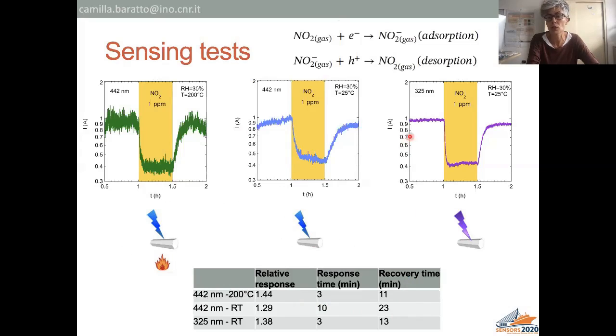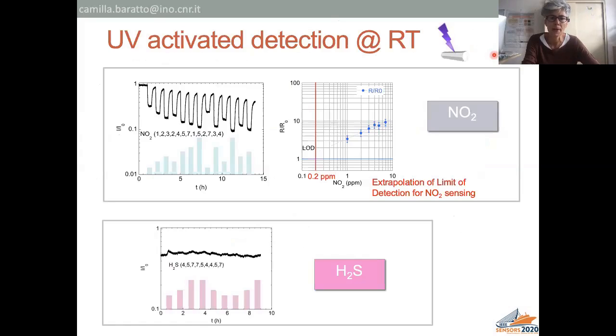But when you shine UV light, the relative response is comparable to the one obtained in the first case, and response and recovery times are also comparable, because with UV light, electron hole pairs that are made available in the conduction band by the UV light shining are available for participation in the adsorption and desorption reaction of NO2 from the gas, from the semiconductor surface.